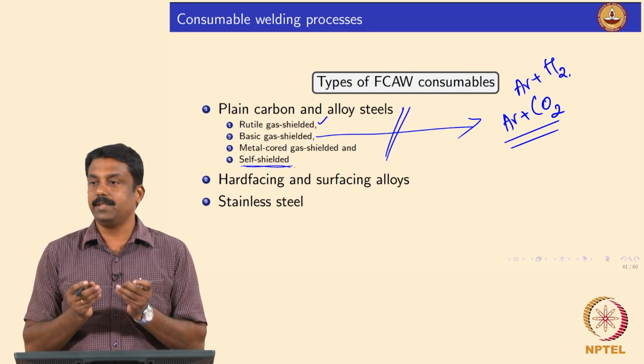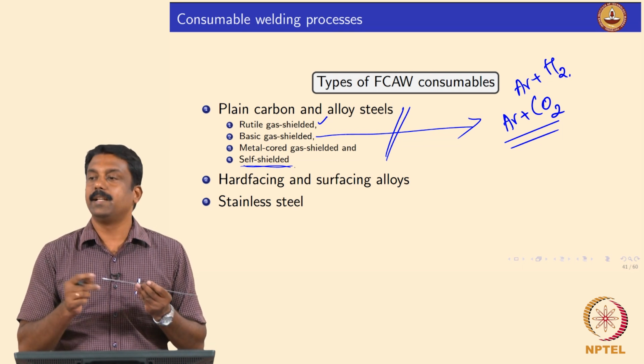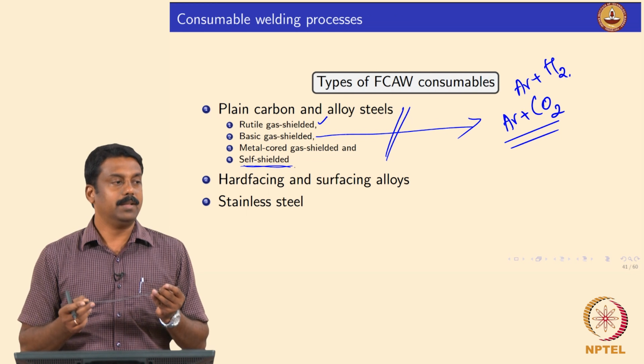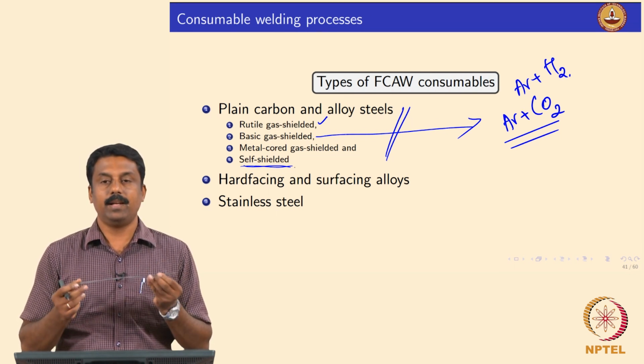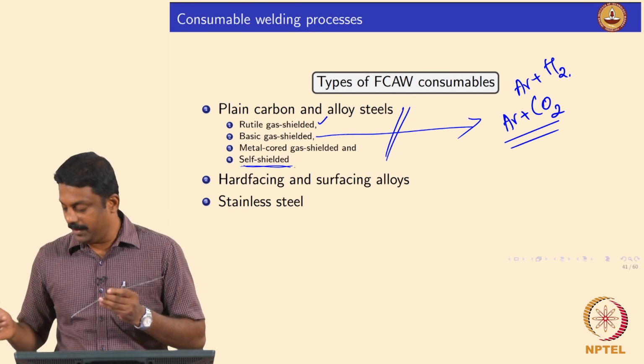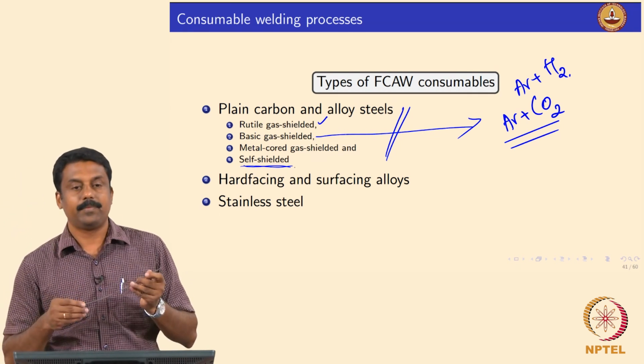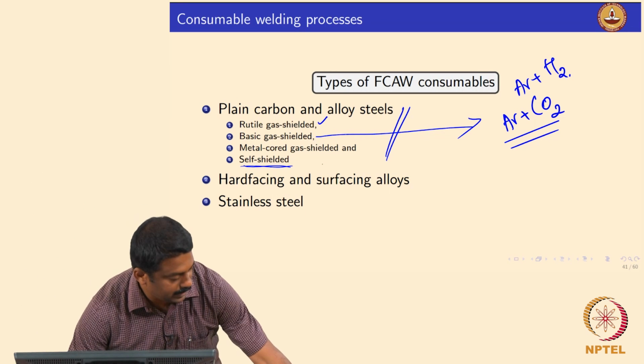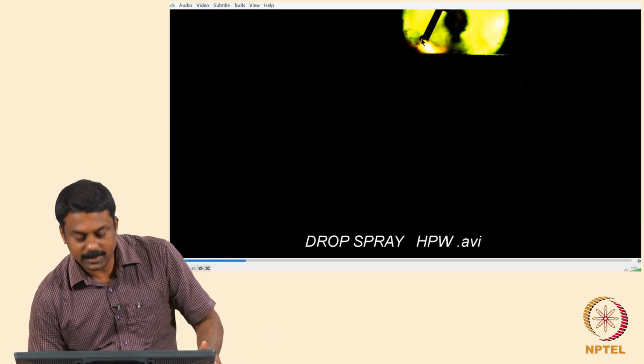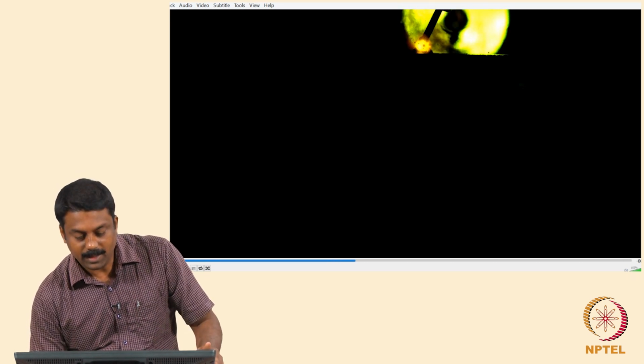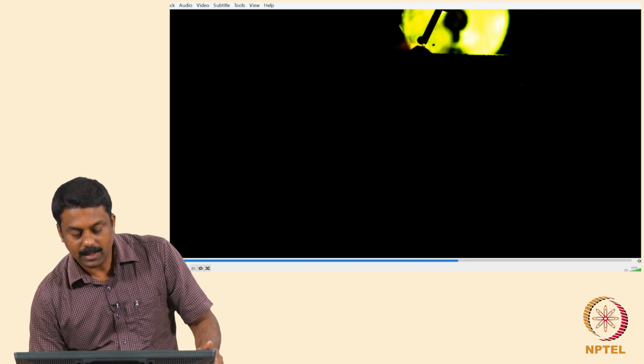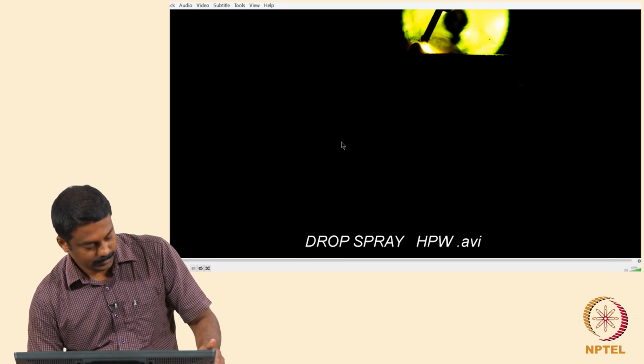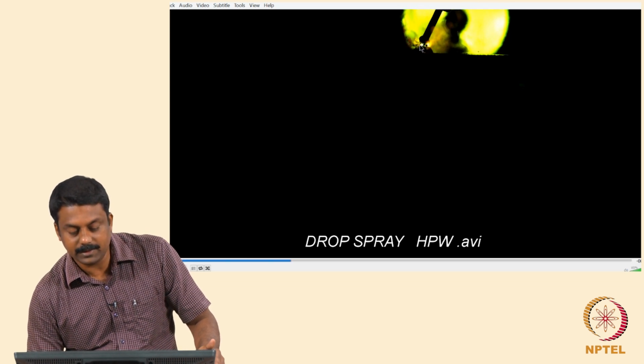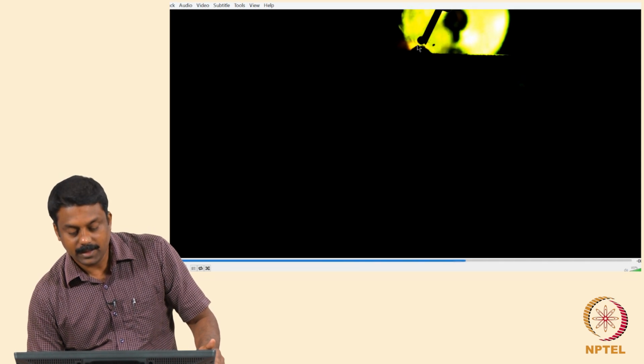because this electrode is self shielded, where the flux inside the core of this electrode burns and generates carbon dioxide. So, this is a self shielded carbon dioxide electrode, and you can see the video of the process when we welded this electrode. So, this is the electrode which I sent around, and you see the metal droplet formed, and in most of the cases the droplet transfer is repelled globular. So, the flux burns and generates the required shielding gas. You see the disintegration of flux, right. The flux actually goes in and then it burns and generates the shielding gas required.